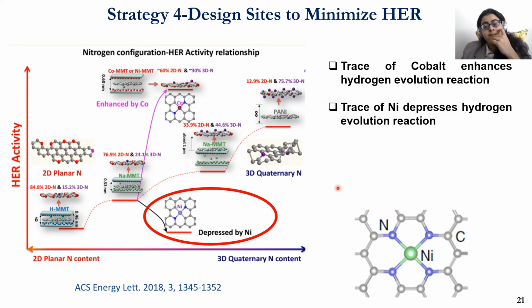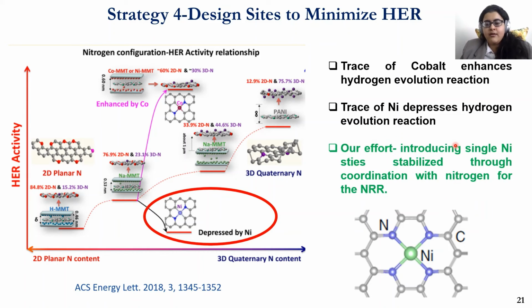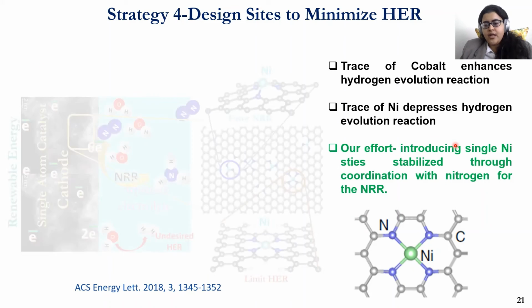We tried to further increase the selectivity by using a different strategy, where I tried to find out what could be the element which can reduce the selectivity of hydrogen evolution reaction. I was reading a paper, and their objective was to increase the hydrogen evolution, and they found that using nickel single atom can actually reduce it. So for them, this was something that they did not appreciate, and they were looking for something like cobalt. But seeing this, I felt like maybe this will be useful to us. We cannot use exactly this, so we tried to find out how we can make something like this, and if it can help in increasing the selectivity of the process. So this was the second work that I published on nitrogen reduction reaction.